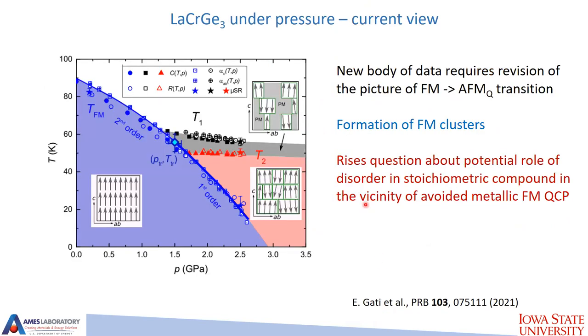The picture we have at this point is the following. We do suppress ferromagnetic order, which starts as second order and becomes first order at some point. Then we have two new phases, one between T1 and T2, and another below T2. At this moment, we think that in this gray phase between T1 and T2, we are forming ferromagnetic-like clusters. Their size is increasing, and we're getting more and more of them. So below T2, ferromagnetic clusters are formed, and on cooling they're just maybe aligning a little bit more. So we think that this phase is not long-range antiferromagnetic order, but rather a phase with ferromagnetic clusters.